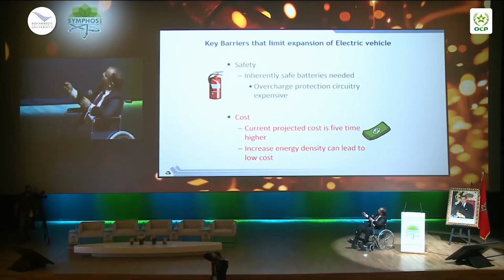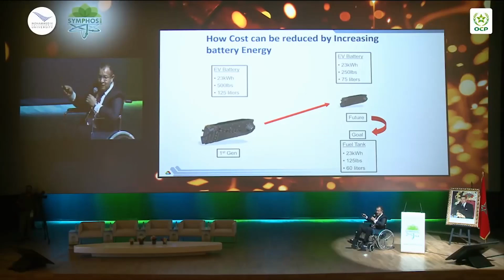So one way of reducing the cost is to increase the energy, as I mentioned. Here is an example. If you take, for example, a pack that belongs to Nissan Leaf, it is a 23 kilowatt hour, 500 pounds and 125 liter. Now imagine if you increase the energy density of the chemistry inside this pack. What will happen is you can still design your 23 kilowatt hour, but your pack becomes smaller, which means the amount of cells becomes less and the amount of material in the cells becomes much less across the board, active and inactive. Not only cathode and anode, but separator, electrolyte, and so on. And you can make some significant cost reduction this way.